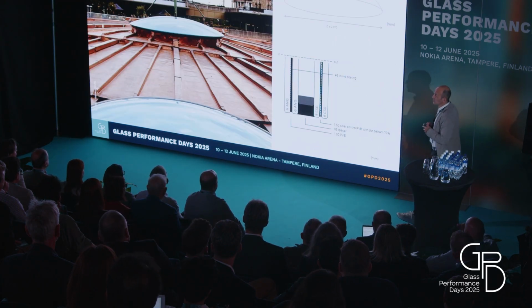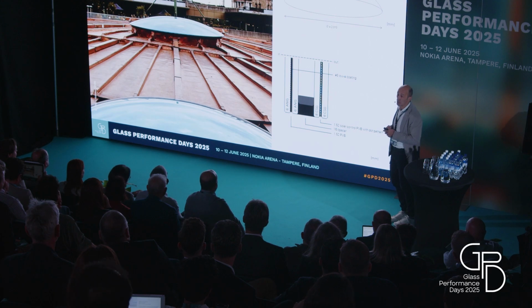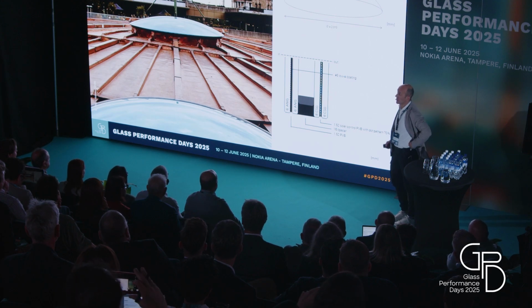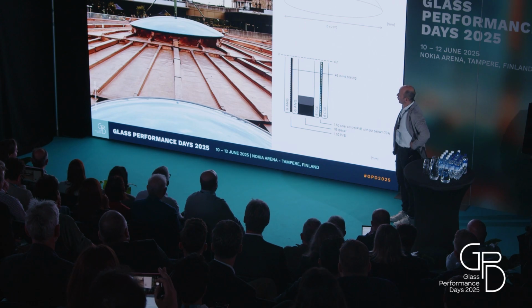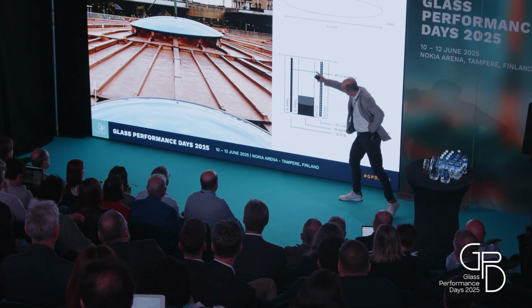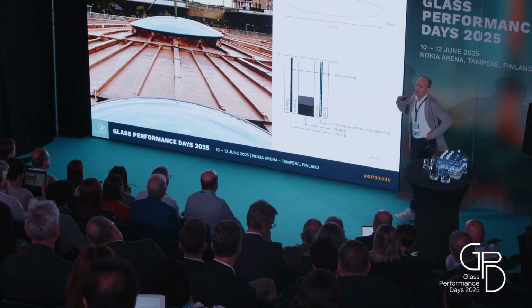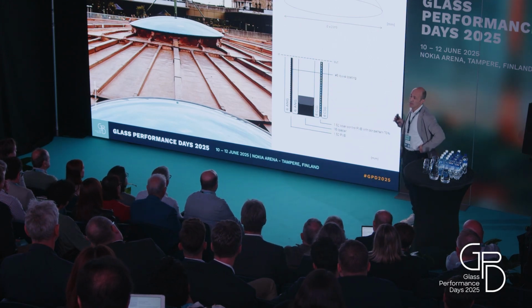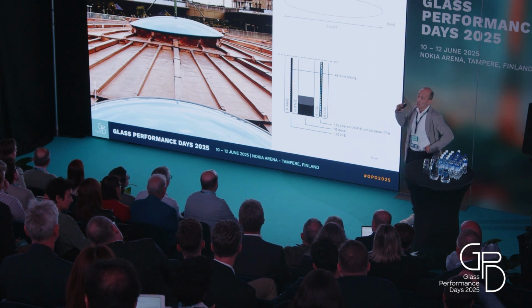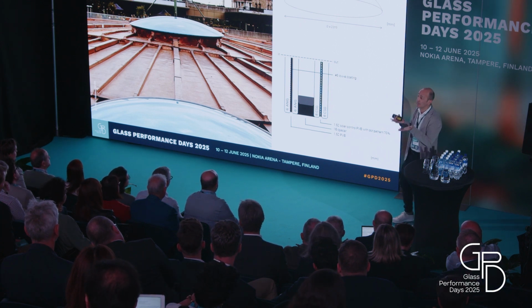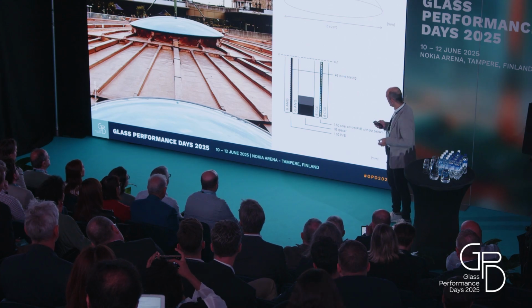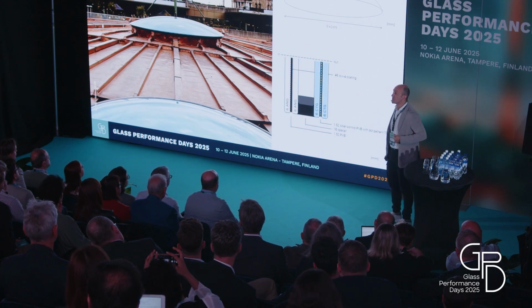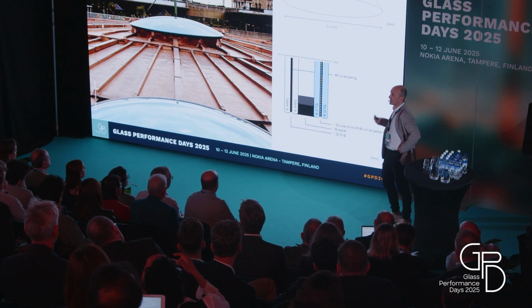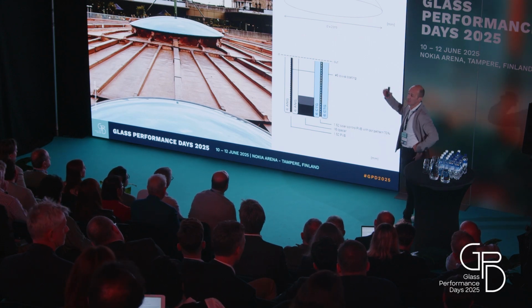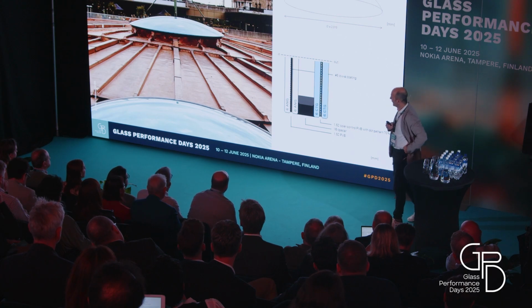A good example of the use of this technique is these circular skylights that we recently delivered to the Museum of London, where the glass is slumped first. The inner set here on the left stays annealed laminated, so gravity bending, annealed laminated with a high-performing Low-E coating on the convex surface facing the argon cavity. But the outer layer is submitted to chemical strengthening so that we can have a glass that is strong enough to withstand any sort of external loads, thermal loads, mechanical loads, any of them.